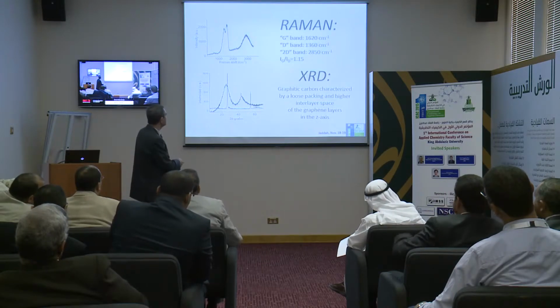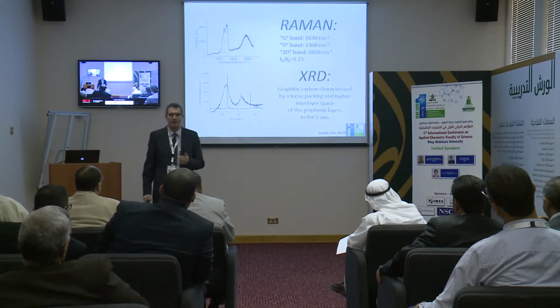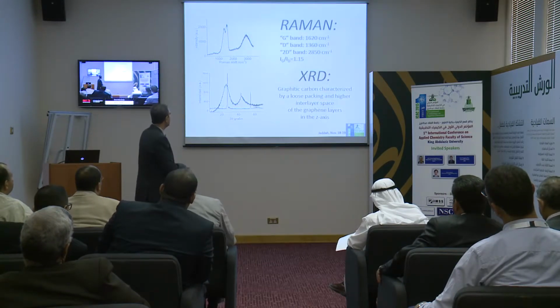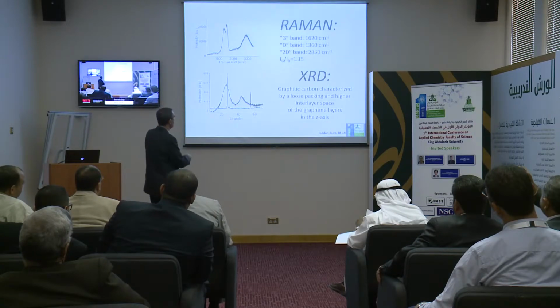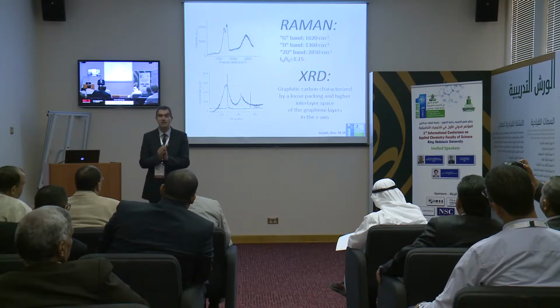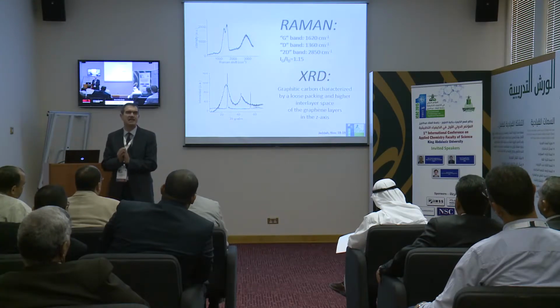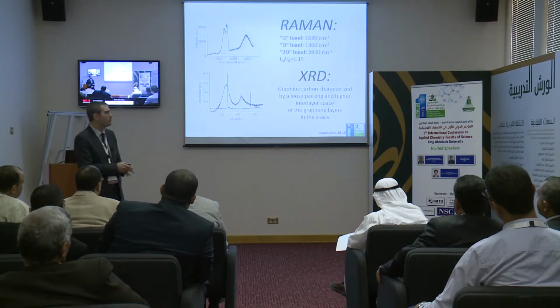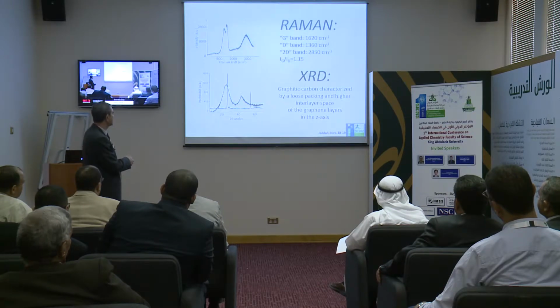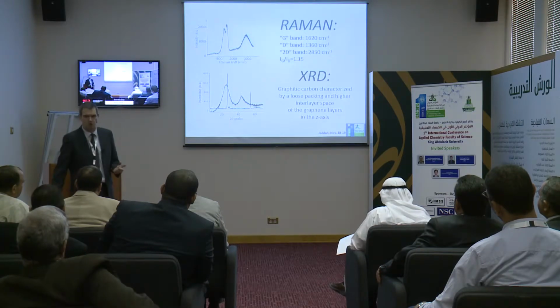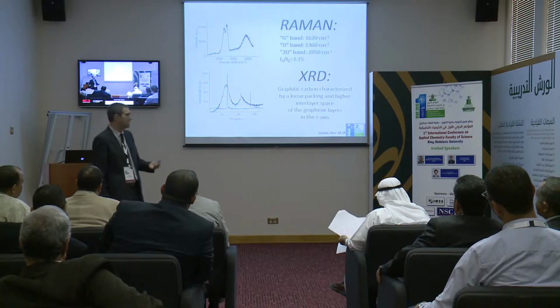This is very interesting. This is the X-ray diffraction of the carbons when it's a powder, compared with the XRD of the graphite. The XRD of the graphite has very sharp lines, so this means that graphite is highly crystalline, and for this reason, when you try to exfoliate or sonicate graphite, it's not possible. The yield of exfoliation is very low.